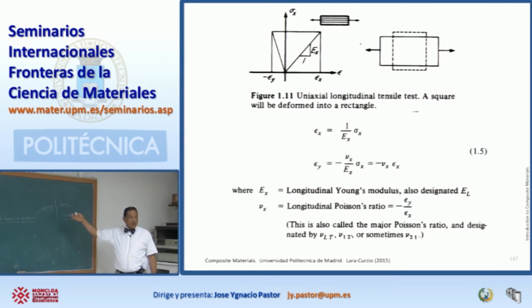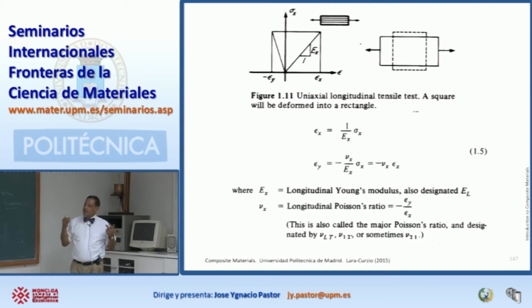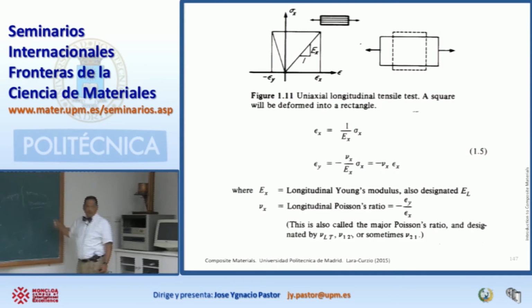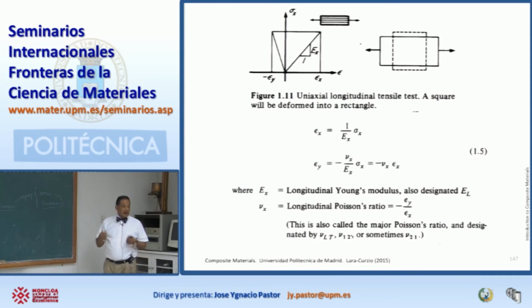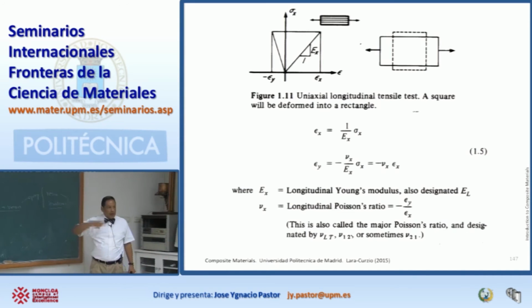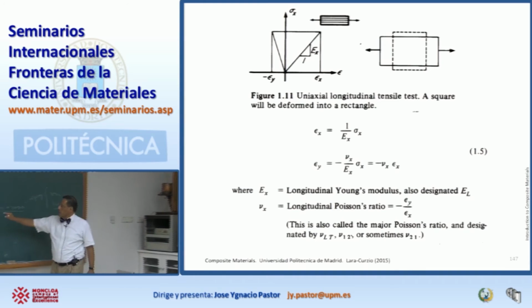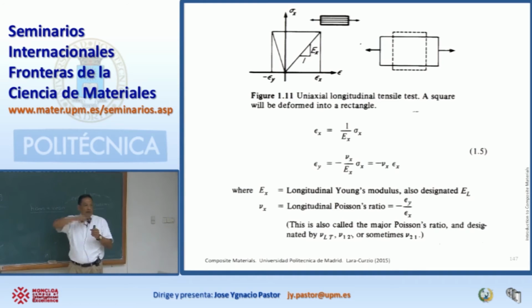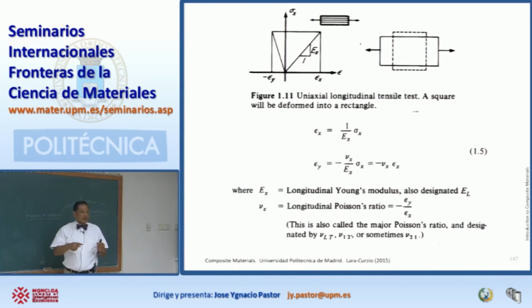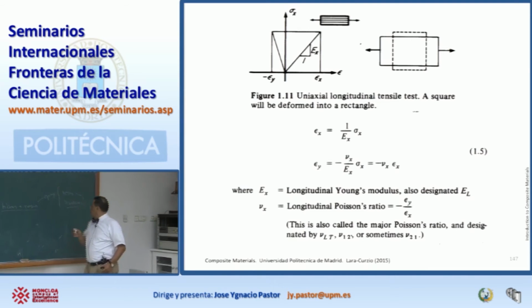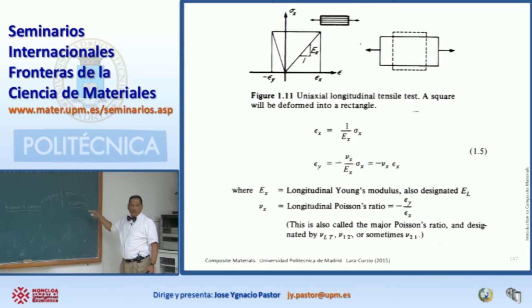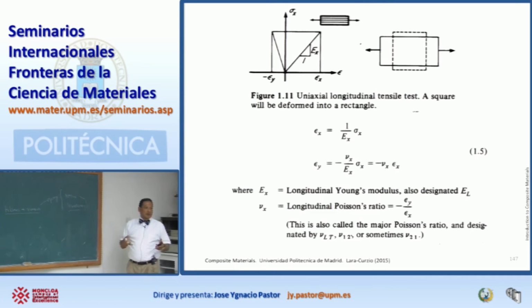Now, if you heat up this system to, let's say, 130 degrees C, the reaction between these two components is going to take place very quickly, and then the resin becomes very hard. So what you saw in that rotating video is you are applying a bunch of pre-preg around the cylinder. Once you have the structure, you take it to the oven, and then the reaction between the resin and the hardener takes place, and the epoxy becomes hard.